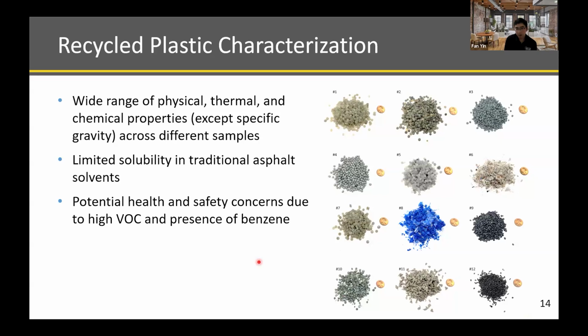Another major finding from this characterization perspective is that the majority of the plastic samples have very limited solubility in traditional asphalt solvent. So if you are using the dry process of adding these pellets into the mixture and hoping that you can do solvent extraction to look into the binder properties, you may want to think twice on that, because the solubility challenge means your extracted binder may not be the same material as what you got in the mixture phase. You can still do the testing and get some results, but it may not be as accurate or as precise as you would hope from the mixture level.